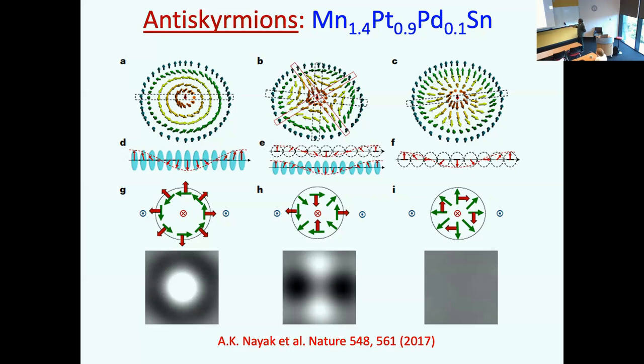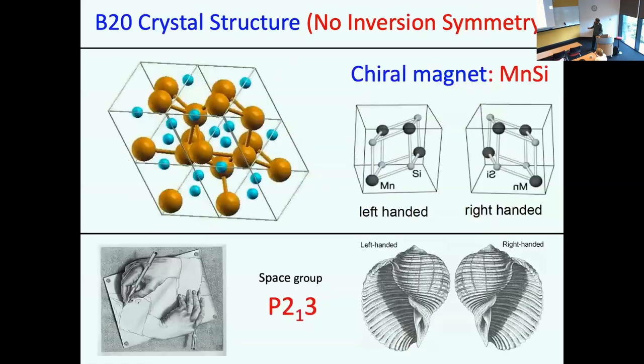Anti-skyrmions are in between somewhere. So the green arrows are the magnetization, and the red arrows are the Lorentz TEM electron deflection. So you get very different images, and you get a combination. If I cut it one way, it looks like a Bloch skyrmion. If I cut another way, it looks like a Néel skyrmion. So a little bit of materials science, what kind of material? This is manganese silicide. You don't have to know the crystal structure.